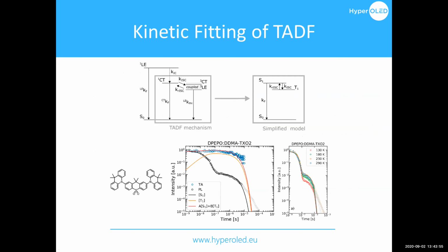So what can you do then to get that number, that reverse intersystem crossing rate constant? Because it turns out that comparing singlet triplet gaps alone really doesn't cut it, because different materials have different degrees of coupling between their different states. So in some early work that I did at Durham, what we did was say, all right, can we do some fancy fitting on the singlet time-resolved photoluminescence and extract the rate of reverse intersystem crossing directly from that?